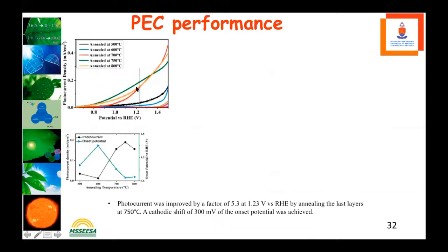All right, now looking at the photocurrent, we have already understood the 500, so we can now compare only the 500 and the 750. You can see that your photocurrent increases when you anneal at a higher temperature of 750 degrees Celsius, while many of the papers that we have used before all anneal at 500 degrees Celsius, which means that they are losing some photocurrent by not going higher.